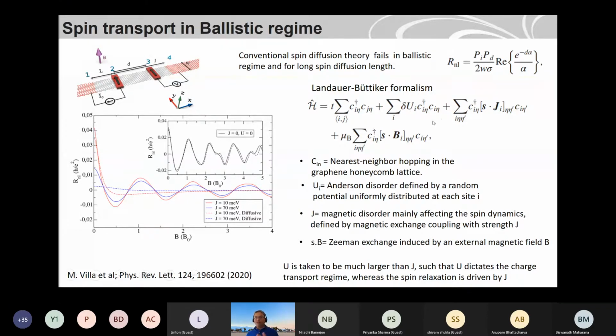So what they have done is put some practical parameters into the equation. J here is the magnetic disorder. If you have, let's say, a very small amount of magnetic impurities, even parts per million, that can also affect the spin transport. And the last term, this S dot B, is the Zeeman exchange when you apply a magnetic field. So here you can take all these different terms with different weightage, so they can calculate with that. For example, if you calculate with, let's say, some magnetic disorder of different quantity, and maybe you can take 0.